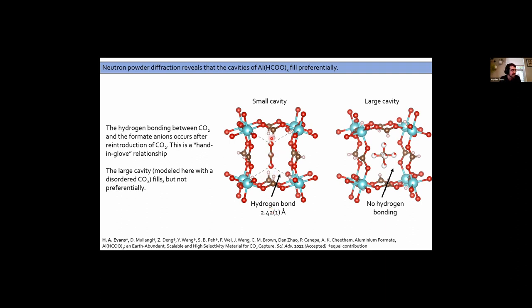But one of the things I skipped over is when you actually make this material straight up, it has CO2 already embedded in it, but people who had discussed these materials prior hadn't figured out how to activate it, which is where our contributions come in here. In the large cavities, you can see there's no hydrogen bonding, right? So the formates point away, and so you only get the disordered crystallographic model of the CO2, and that's a tumbling density of the CO2 in here.